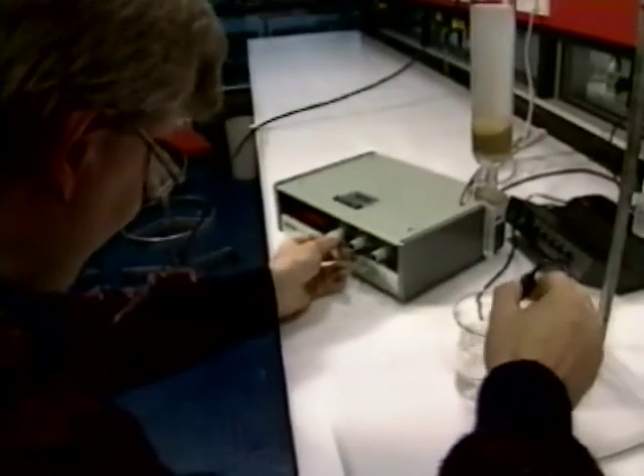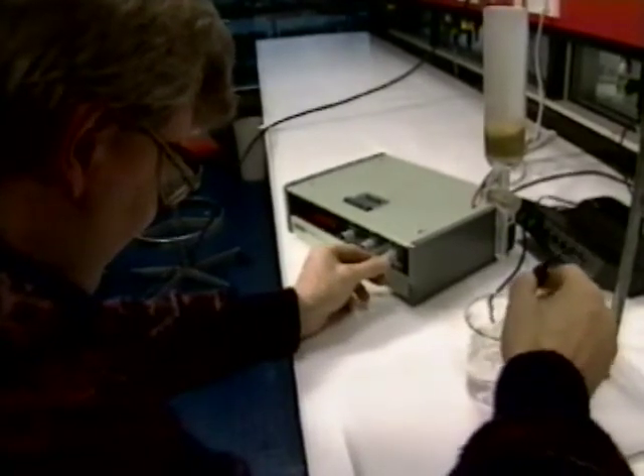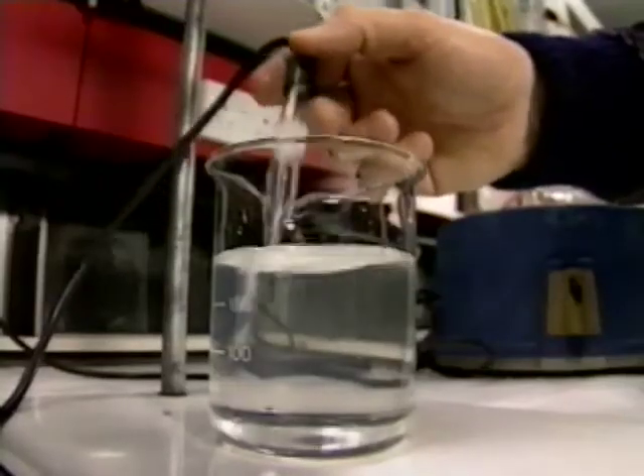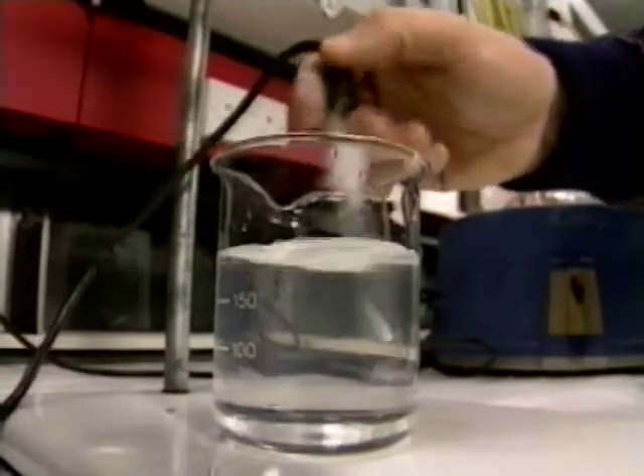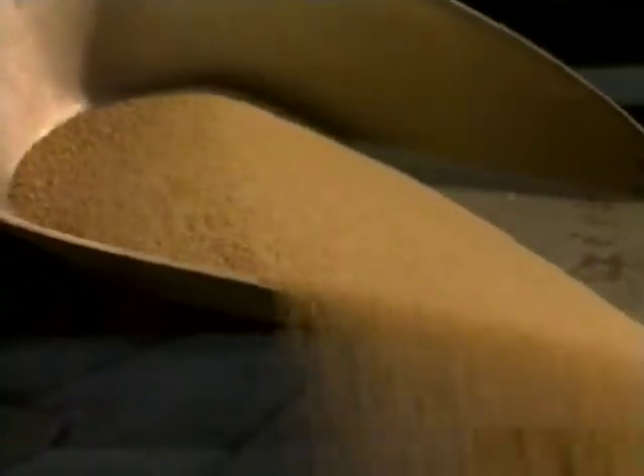Another key property is the fracture toughness. If the abrasive is too weak or the surface too strong, then the impacting particle will shatter into fine dust and cause no damage to the scale. The result of this scientific study was to design an abrasive material with all the right properties to remove the scale from the tubing without damage to the steel surface. This material is sterling beads.